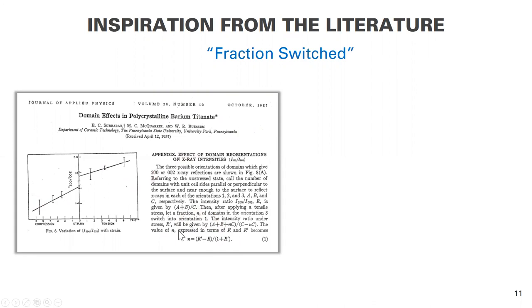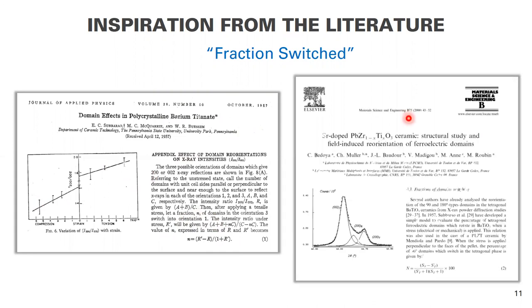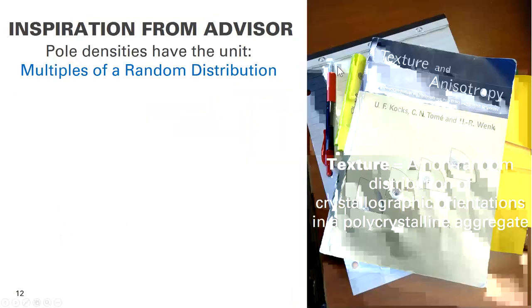And so the authors go through and create a very nice way of describing the fraction of domains that have switched. And then in later work, for example, this paper in 2000 by Bedoya, they take yet another approach for describing the fractions of domains that are switched. Now, we're not going to dig into these two equations today because that would take an hour in and of itself. But mainly I want to point to the fact that in this community, there's a tendency to talk about the fraction of these domains that have switched, or the volume fraction that switched.